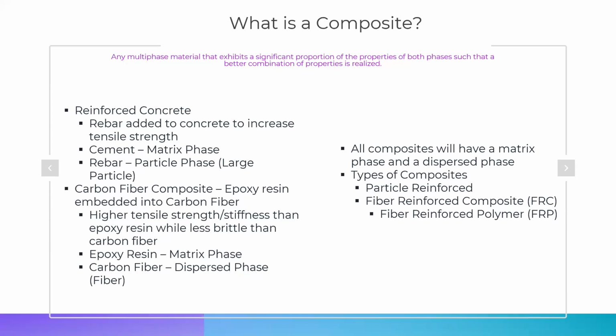Pretty much, you have cement or Portland cement mixed with the rebar. So the rebar is the fibers and the Portland cement is the matrix. So in our case, we have an epoxy matrix with a carbon fiber disperse phase, which is the fibers. So the fibers is what gives it the strength, and the epoxy is what allows it to stick to the metal and also gives it the chemical and temperature resistance.